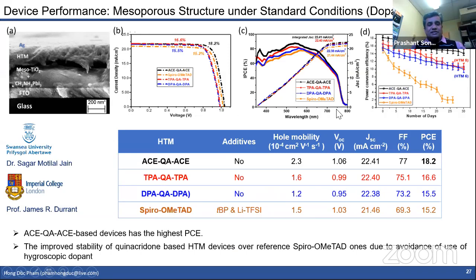Looking at these 3 materials, this time we got an efficiency of 18.2% for one of the compounds. Now we have moved from 17 to 18.2, and look at this. In this case, the relative humidity is much higher than the earlier case. It is 75%, and still you can see how HTM 4, 5, 6, these 3 compounds, are stable compared to the Spiro.